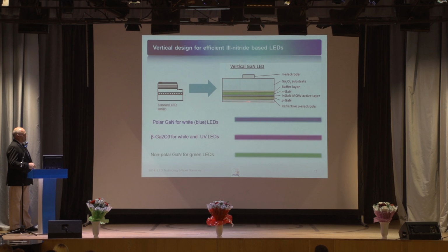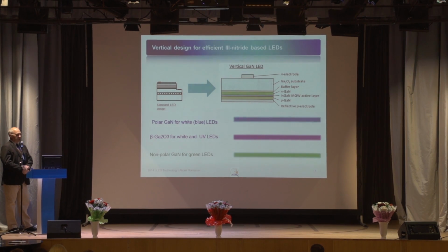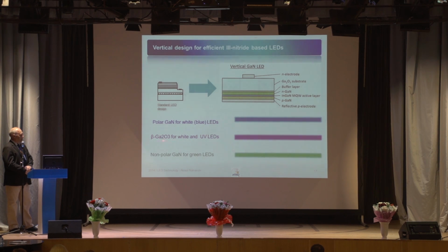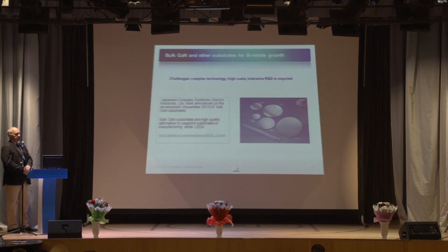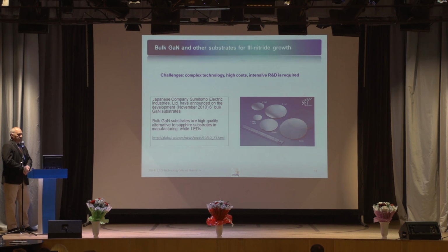And of course, another thing which is also given in this figure is the use of different types of substrate. Instead of using the sapphire substrate, it is possible to use a so-called homo substrate, a gallium nitride substrate, which will be good for blue LEDs. Then, in principle, it is expected to apply gallium oxide, which is quite a new material, and I will talk about this very soon, for UV LEDs, and also to use so-called non-polar oriented substrate for the green LEDs. Therefore, use of different substrate material is very perspective and promising.